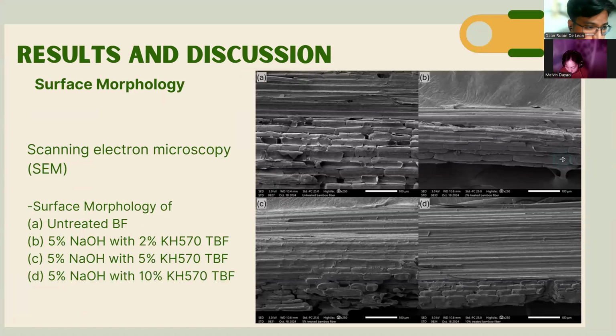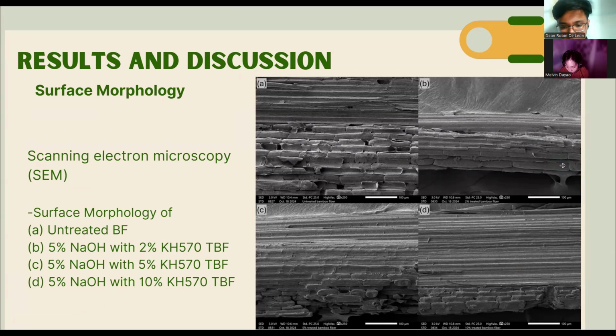Moving on to the results of the scanning electron microscopy. In Figure A, the untreated bamboo fibers have a rough and sharp structure compared to the smooth surface of the treated fibers in Figures B, C, and D. Moreover, the surface of the treated fibers became progressively smoother as the concentration of the KH570 increased, and furthermore, impurities are present throughout the samples, but more are eliminated as the KH570 concentration increased, which can be observed in the bumps on the cellulose microfibrils and the lumen structures. The cellulose microfibrils are the elongated parallel lines, while the lumen structures are short rounded rectangles.